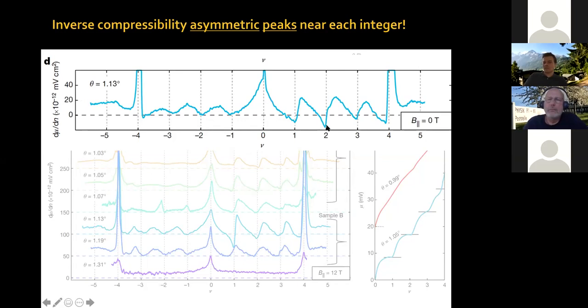So this is something which is characteristic of interactions, and although in this first paper we didn't point this out, this is a behavior that we're now exploring in more detail, and we will have more to say about it soon. But indeed, this negative compressibility has to do with this model where you have Coulomb interactions, and this band structure is the zeroth order model, which explains some of the phenomenology, the peaks. There are a lot of other things in the phenomenology, for example negative inverse compressibility and where these peaks exactly occur, for which you have to introduce the long-range part of the Coulomb interaction and other things in a more sophisticated model. And we're working on that now.